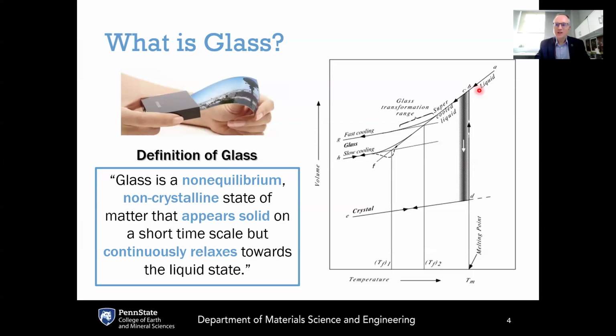Now, crystallization is not something that happens instantaneously. Crystallization takes time because it takes time for the atoms in the liquid to move around and rearrange themselves into a crystalline lattice. What happens if you take a liquid and you cool it so fast through this gray region where crystallization is likely? You cool it so fast that you don't give the liquid enough time to crystallize. Then what we get is a phase called a supercooled liquid. A supercooled liquid is just a liquid that is cooled below its normal freezing point.